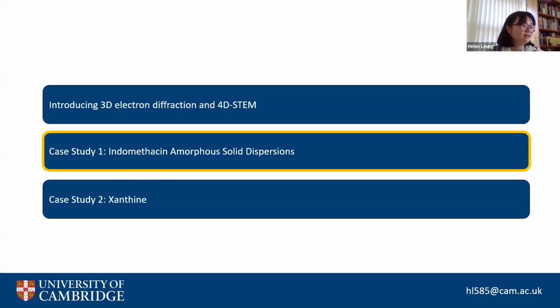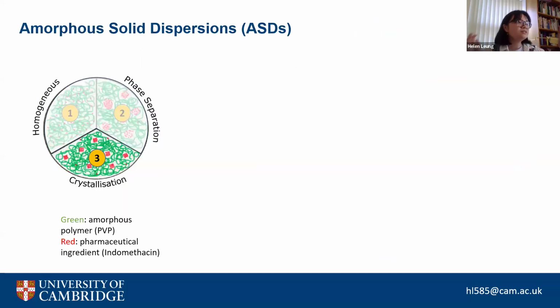Okay, so going on to our first application, indomethacin. Amorphous solid dispersions are a formulation type, and they are used for any sort of drug which has very poor aqueous solubility. These drugs are normally ingested, so you would take them orally. And of course, if they've got poor solubility, by the time they get to your gastrointestinal tract, the passing of the drug into your blood is dependent on that solubility somewhat. So if we have a drug with poor solubility, we might wrap it into a solid dispersion and fill it with an excipient, which is a polymer. In this case, we used PVP. Ideally, you get what we have in section number 1 here, which I have labeled homogeneous, a very evenly dispersed amorphous mixture, which has superior solubility properties.